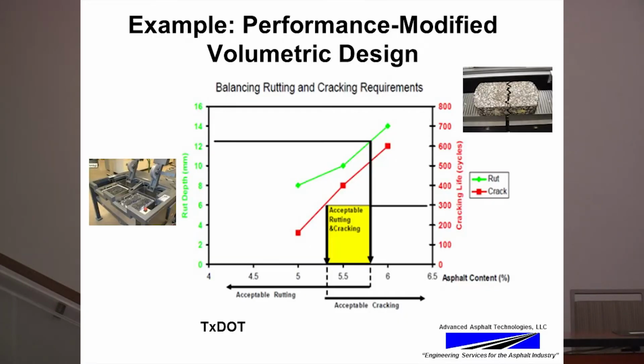A second one is an example of how you would do the performance modified volumetric design, and this is some information that came from TxDOT. What they use is, again, the Hamburg wheel tracking device for rutting resistance. For cracking resistance, they're using the overlay tester. So if you look at the green curve, what they do is a volumetric design at the optimum asphalt content plus and minus 0.5%. They run the performance tests.